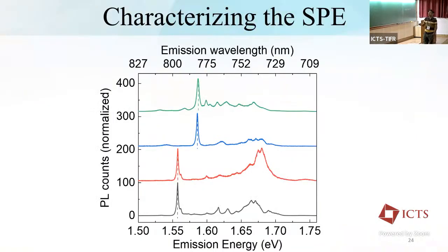Okay, so these are the spectral features that I was talking about. You see the exciton, which you hardly see, this is the free exciton. It's about 1.75 electron volt at low temperature. And this is, by the way, like a 4 Kelvin or so measurement. And these are the sharp peaks that I'm talking about. So this is about 200 meV below this. And these are different pillars.